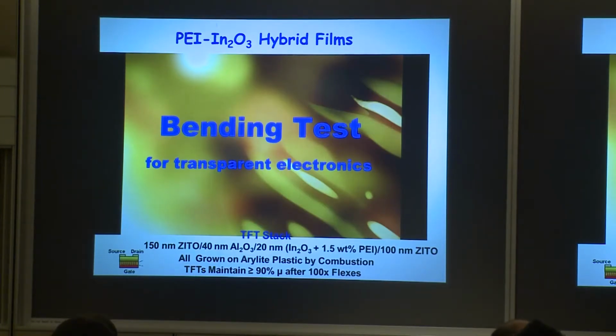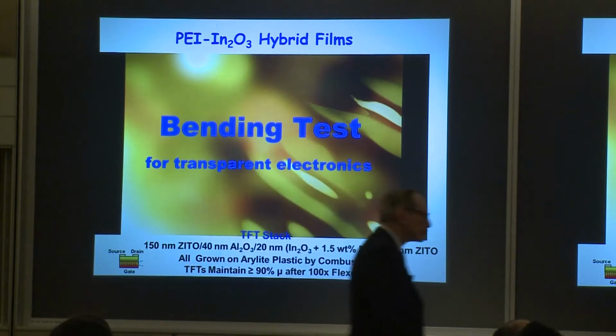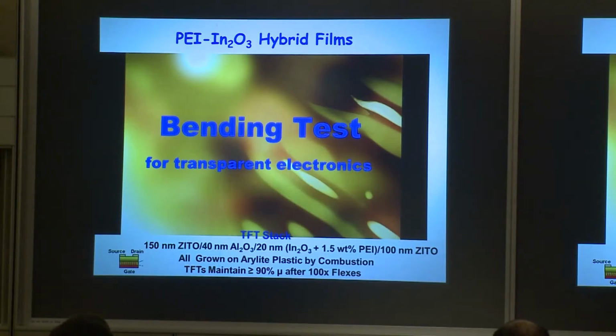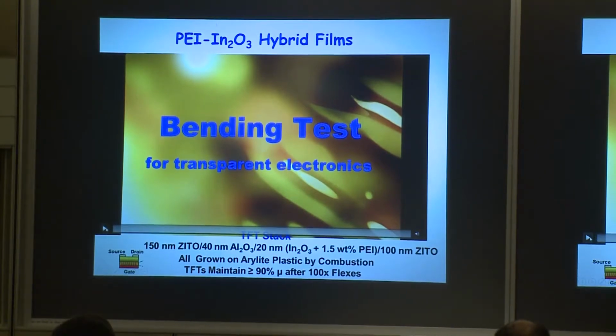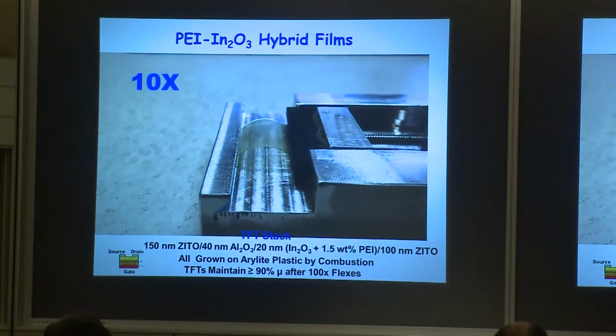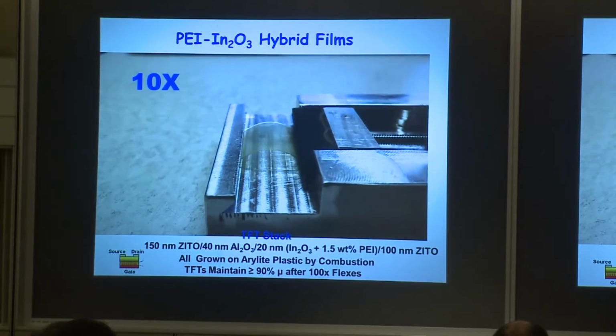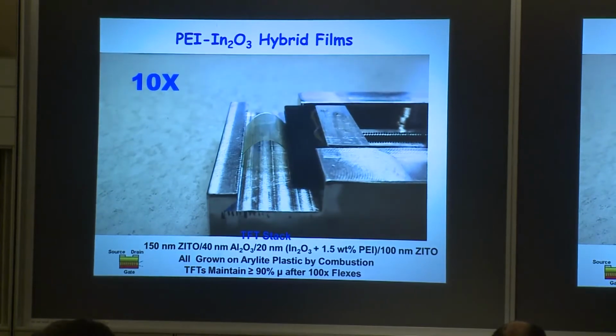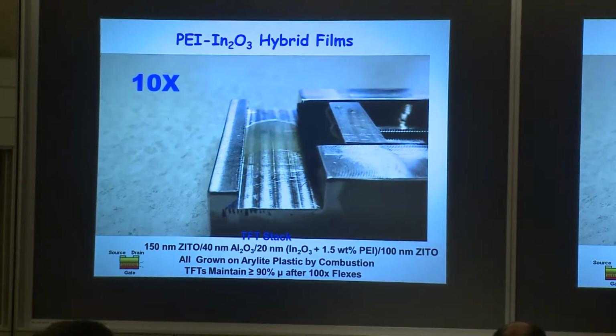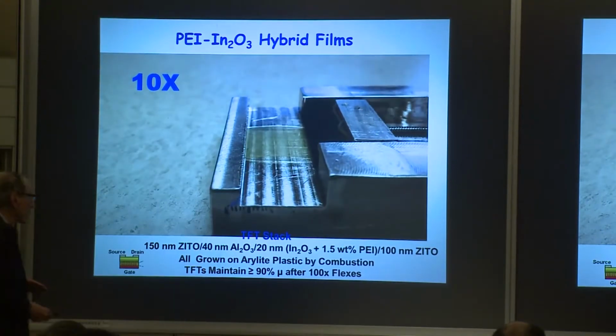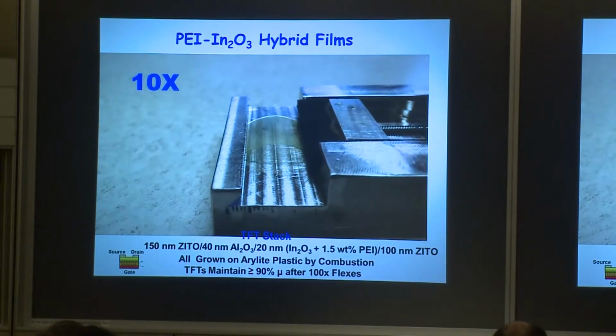This is, let's see if I can. So this is a bending test. It's these transistors on, okay, it's going to work. On plastic, on Arylite. So this is the transistor. The indium oxide is doped with a little PEI to reduce the off current, but also to make it a little more flexible. And so the yellow is due to the PEI. It's not as if we've contaminated this. You want to see it again, or you see?